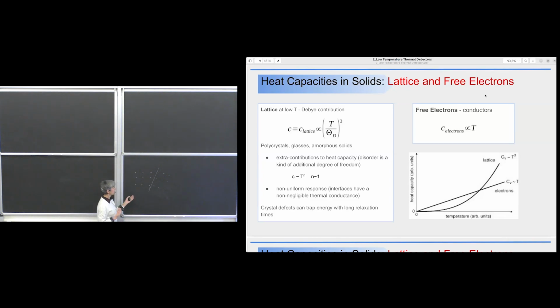thermal cycles can break a crystal, even break or create a dislocation or a deformation of the lattice. It depends on the kind of crystal that you are using. So this is only for the contribution of lattice. Then, if you have free electrons, you have additional degrees of freedom. That means an additional contribution to the heat capacity. And this contribution increases with temperature linearly.